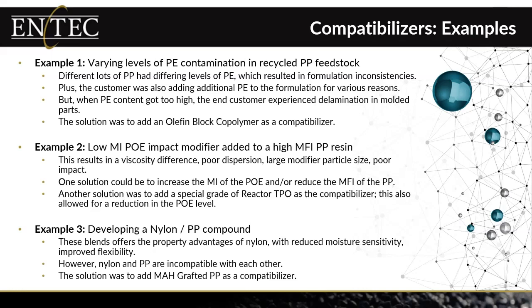And so in the next couple of slides, I've got a number of examples to show you some of the thought process on taking a look at where you would look at compatibilizers in a different type. So in the first example, I had a customer that would receive their polypropylene or recycled polypropylene feedstock, but it had varying levels of polyethylene in it. So it made it difficult for them to formulate because it could vary greatly from load to load. And in addition to that, they were adding additional polyethylene to their formulation for some specific reasons. But what happened then is when their customers got a product that had too high of a polyethylene level in it, they started to see delamination in their molded parts.